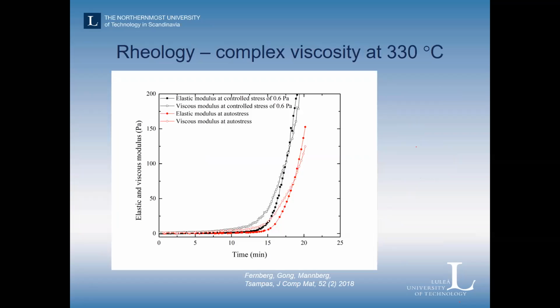So, two modes. The first one, the complex viscosity, we've been using primarily to estimate the time to gelation of a curing system, in order to understand how much time we have for processing these materials. So these are complex viscosity measurements made at 330 degrees. So it's not where we have the highest reaction rate, but we notice that in these cases we determine this. This is for elastic and viscous modulus, and the filled circles are for the elastic part, and the viscous part is the open circles.